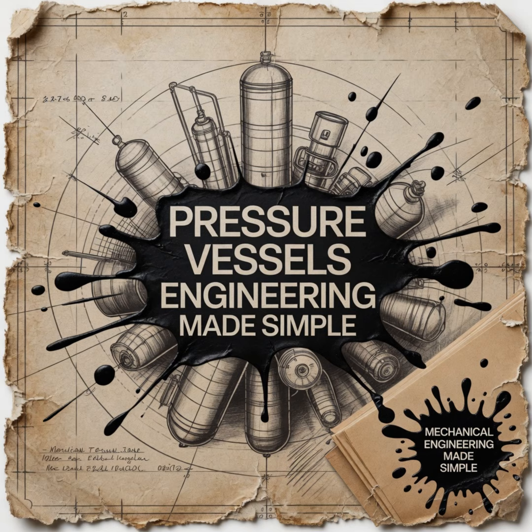Exactly. But a recipe is useless if you haven't proven it actually tastes good. Right. That's where the PQR comes in, right? Yes. The PQR is the procedure qualification record. It is the empirical proof. How do they prove it? To get a PQR, the manufacturer has to take two test plates of the exact material, weld them together in a lab using the exact parameters of the WPS, and then cut that weld apart and test it to destruction. They pull it in a tensile machine to prove it meets the required strength. They bend it to prove its ductility. If the test piece passes, the PQR becomes the legal document validating the WPS.